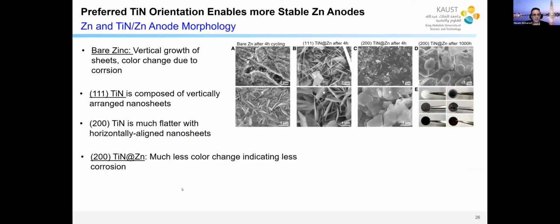So to understand why this happens, we looked at the morphology. The first column here, A, shows you the bare zinc. With cycling, we basically have zinc flakes, these vertically oriented flakes that deposit on the zinc. And for 111 orientation, which is the second column right here, the same story. We have these vertically oriented flakes. But in the 200 titanium nitride, we actually have these platelets lying flat. They lie flat instead of vertically. And you can go to 1,000 hours of cycling here, and you'll see they will still lay flat.